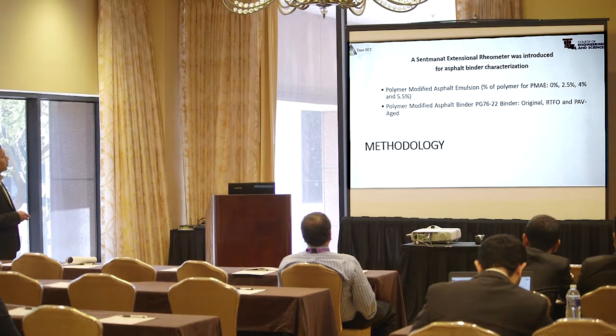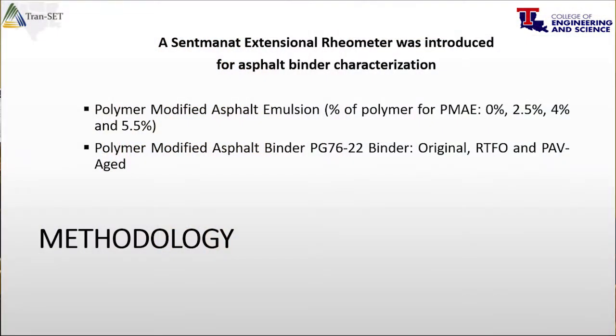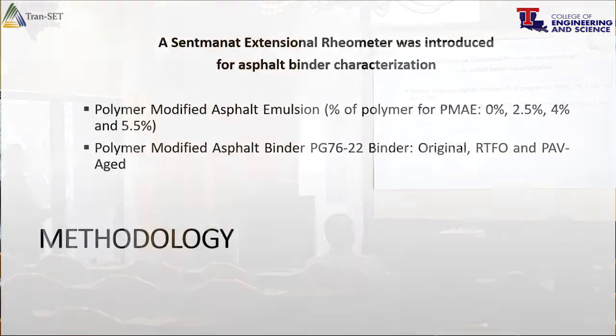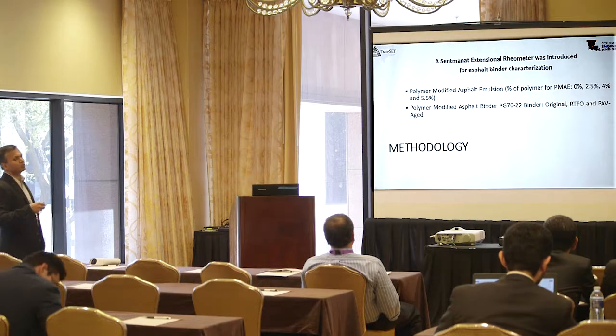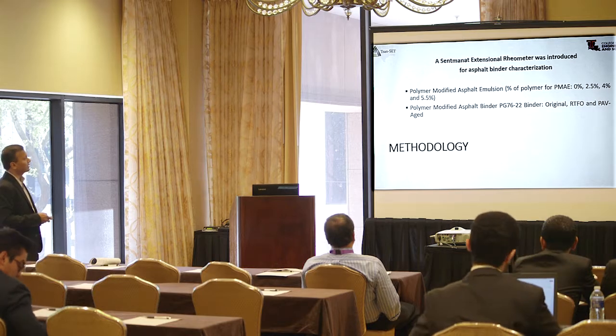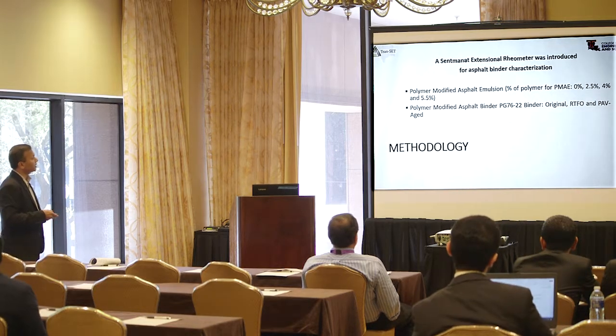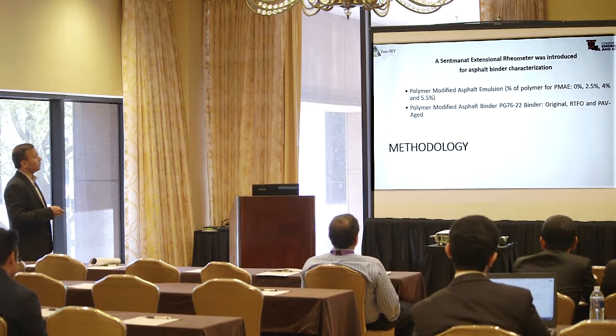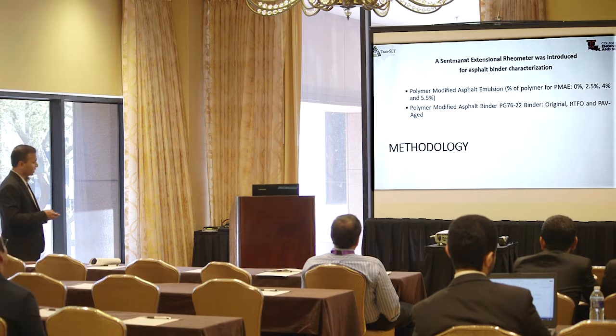And we used polymer modified asphalt binder also, which is PG 76-22, and we aged that, original, RTFO and PAV aged. Here we just checked how our forces are changing with respect to percent of polymer, so that we can use this test to know how much polymer is there really in the film. And then also this one is how our aging changes the force peaks.